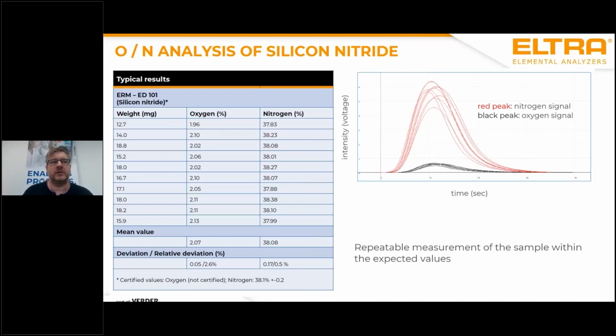On the left side, you see some typical sample weights. Due to the very high nitrogen content, you have to reduce the typical sample amount, and in this case it's about 12 milligrams up to 18 milligrams, and you get quite repeatable results for nitrogen and oxygen. And this means, for example, that you have an RSD for typical measurements, for nitrogen 0.5%, and for oxygen it's 2.6%. Keep in mind that the oxygen content was not certified here. So for your sample, it could mean that the repeatability is even better, or maybe when it's a sample from a production, it could be even worse. But it just should illustrate that we can perform this measurement in a very, very stable way.